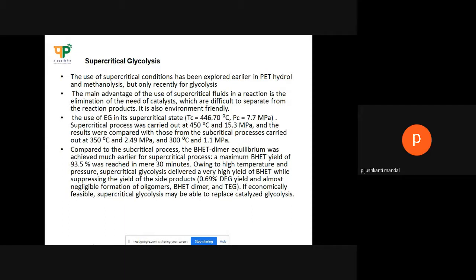The supercritical process was carried out at 450 degrees centigrade and 15.3 megapascal pressure. They compared it with the subcritical process, where the BHET dimer equilibrium was achieved much earlier. For the supercritical process, the BHET yield was 93.5%. This is in a very short time, within 30 minutes, by the glycolysis process. Owing to the high temperature and pressure, supercritical glycolysis delivered a very high yield of BHET monomer.